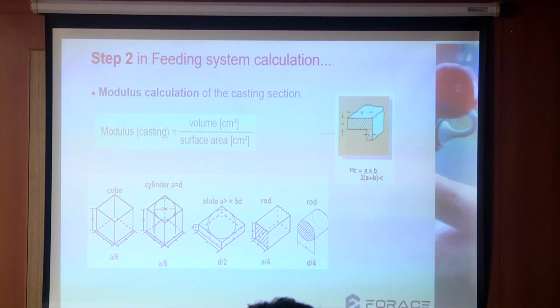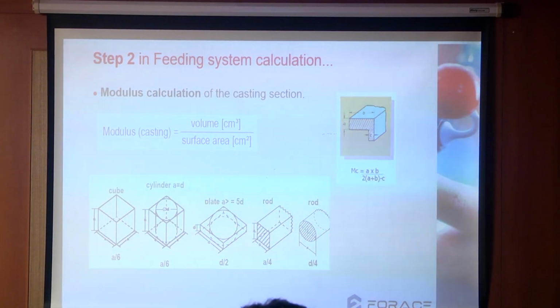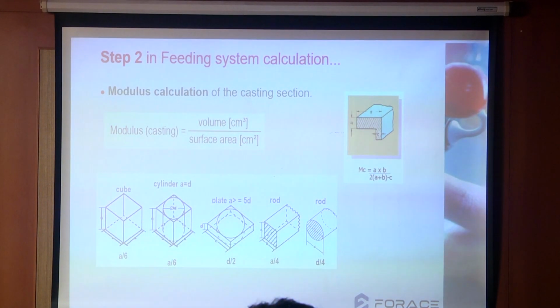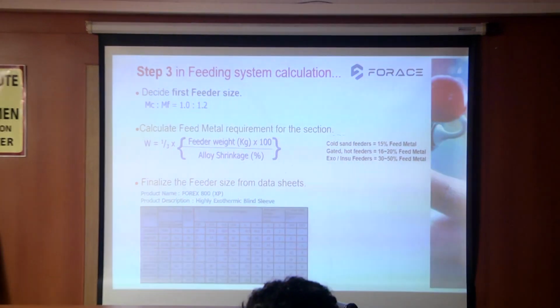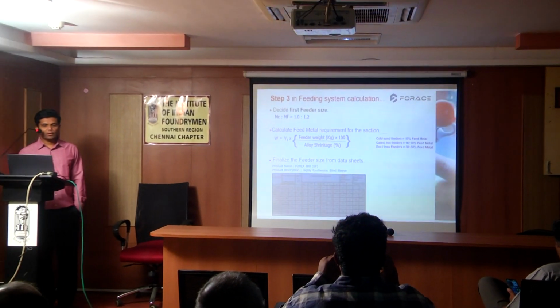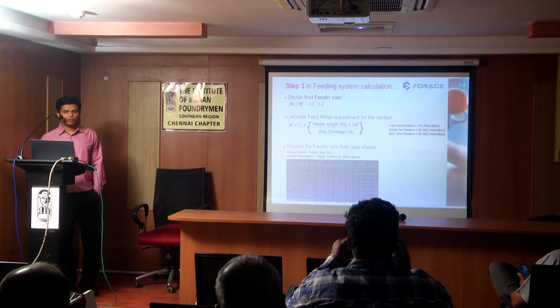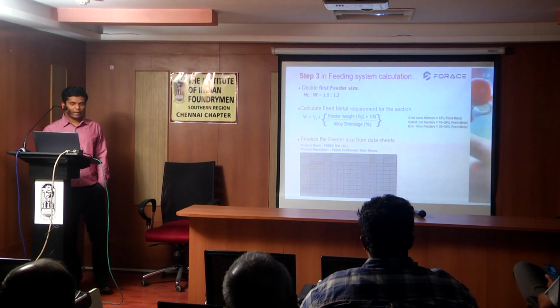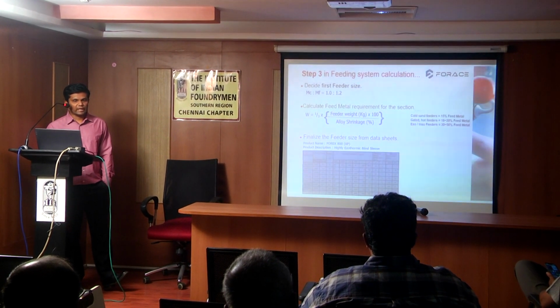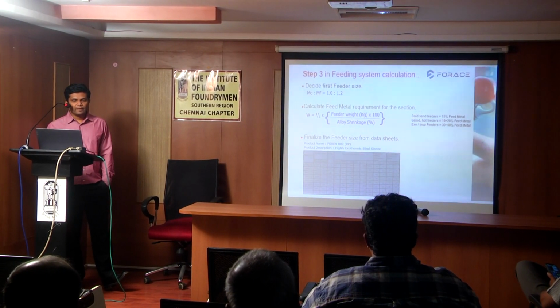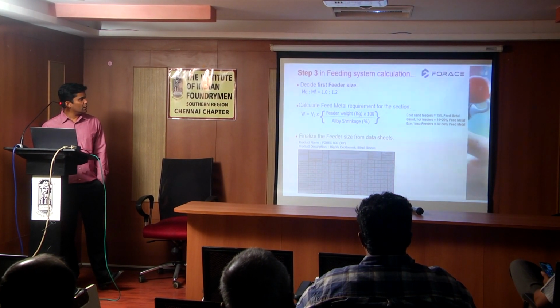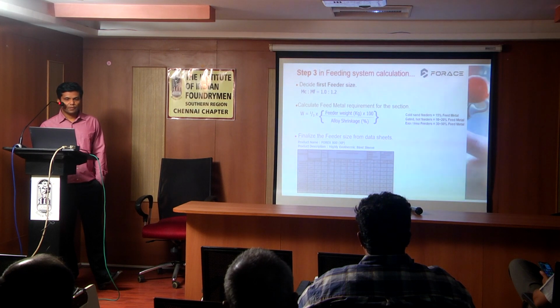Then the second step will be you have to calculate the modulus of the casting, or it's better to go for the calculation of the section or the hotspot. Then according to the casting modulus, you have to increase the modulus or select the greater modulus of the sand riser or the sleeve riser. Then you can get one size of the sleeve.